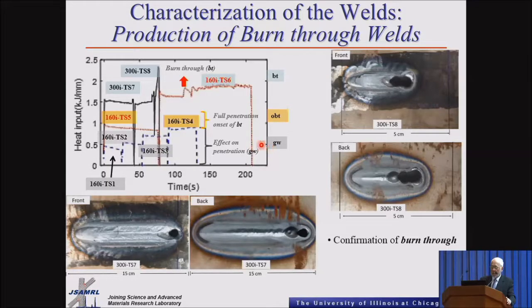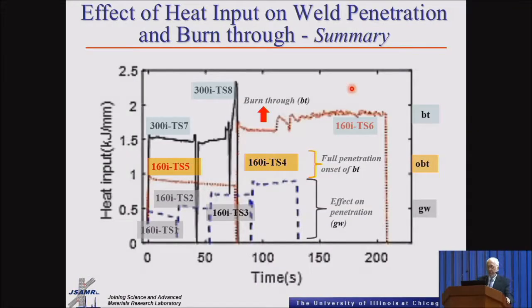So again, low heat inputs are going to give you a good weld. In between is going to give you the onset of burn through, and then burn through is when you have a hole really formed. So this pretty much summarizes what I have just said. Any type of heat input around this range in here is going to give you some type of onset of burn through. Any type of heat input below this one is going to give you a good weld, and then you're going to have a burn through when you have this range of heat inputs.